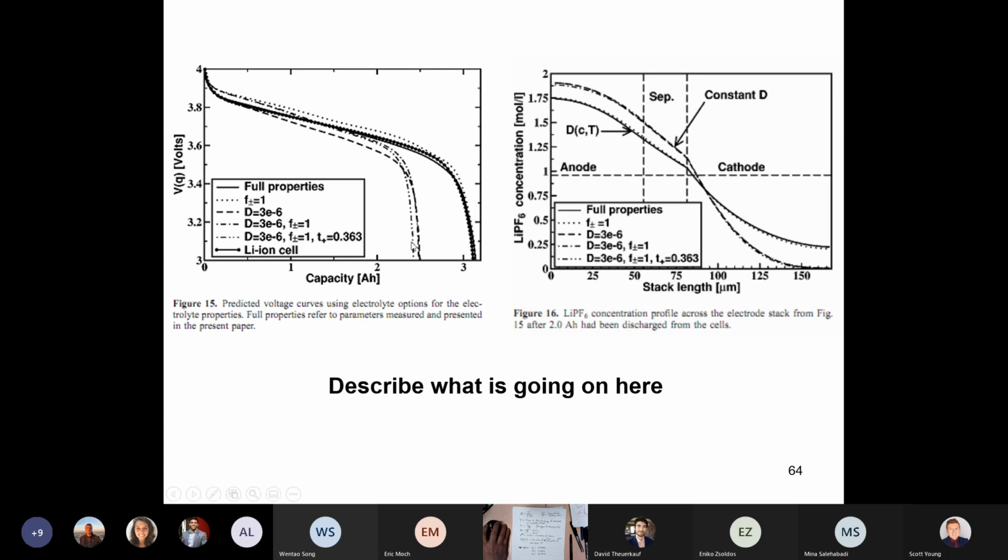So in our baby model about the limiting current in the electrolyte, we would assume a straight line from the max concentration to 0 across the electrode. And it will be interesting to see how close to the max current that we would predict with our simple model this current that he's actually selected is.